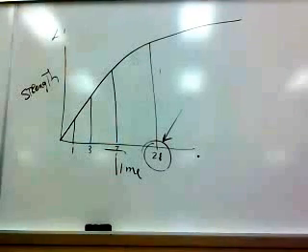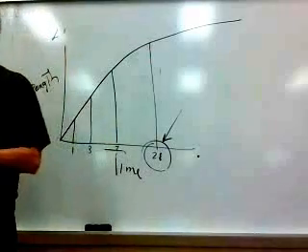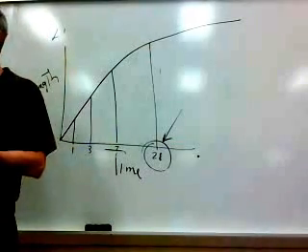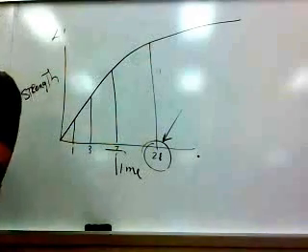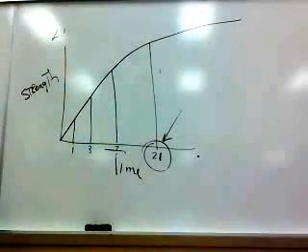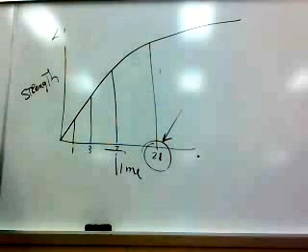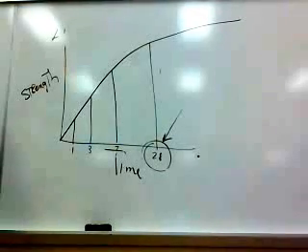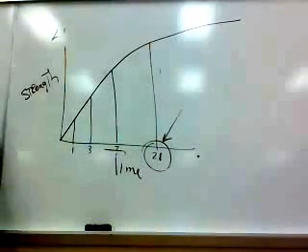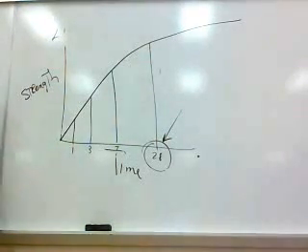When they do quality control testing of concrete, it's not unusual for them to take maybe 4 or 5 cylinders, maybe test a cylinder at 3 days, another one at 7 days, then a couple at 28 days, just because they're gauging those early cylinders to give them a preview of what might be happening later on in their test. So strength is important for us, and specifying strength.